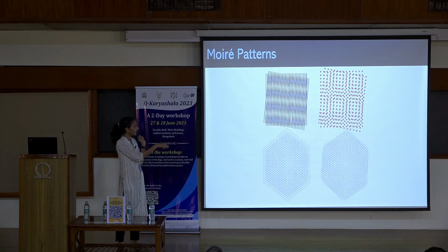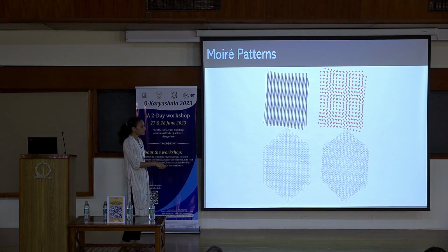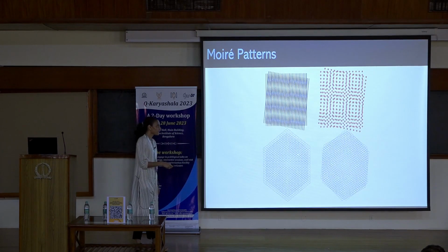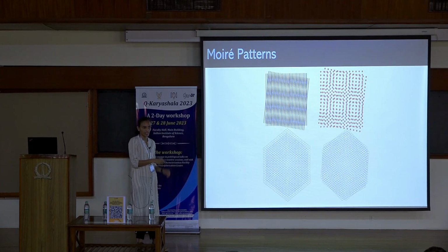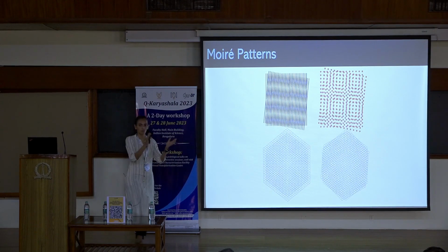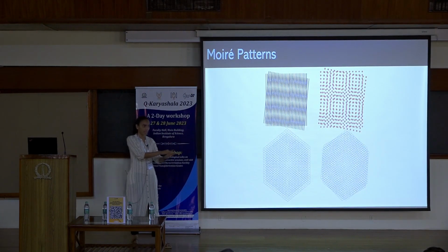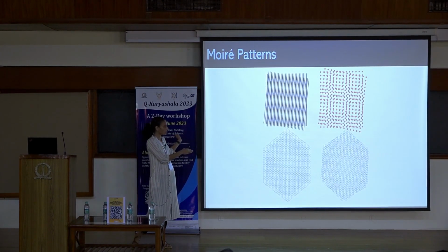So here you have 2 lines which are overlaid, and you see this larger structure that appears, right? Here again, a set of square lattice which is rotated now, and you see this picture. So similarly, if you take graphene and boron nitride, they have very similar lattice constant but not exact. So if you place a graphene exactly with no rotation on top of each other, you will have a moiré pattern like this. Similarly, you take 2 graphene layers and rotate them with respect to each other. Again, you will have a moiré pattern like this, which is what I showed you earlier.